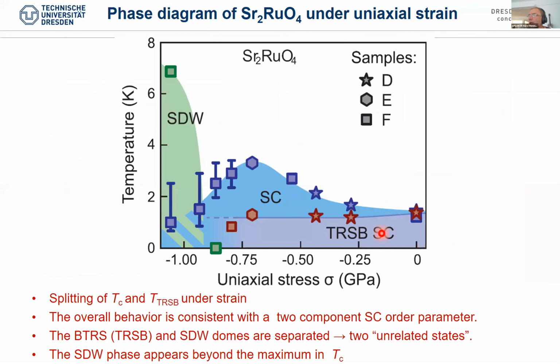And yeah, this is the final phase diagram which we have determined in this study. So we have reconfirmed in our in situ AC susceptibility measurement that there is, of course, a strong maximum in the TC, roughly at minus 0.6 to minus 0.75 gigapascal. We definitely observed a splitting between TC and time reversal symmetry breaking, which increases with strain. And at very high strain, namely at minus 1 gigapascal, we observed spin density wave magnetic order. In our interpretation, this really competes with the superconducting phase at lower strain.